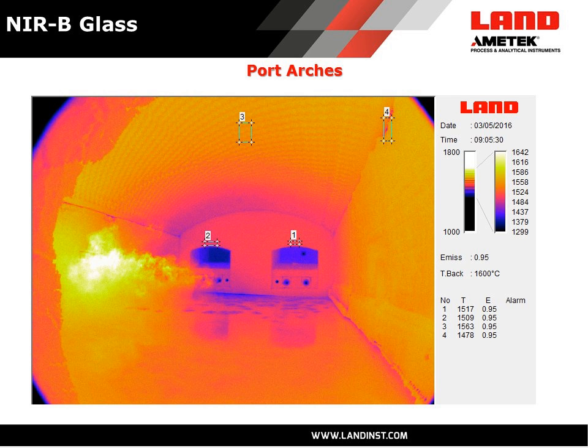Okay, so with this in mind, here's a thermal image of another end-fired glass tank. It's another customer. And in this particular case, they have set up 4 areas of interest within the scene. The first 2 areas of interest here are at the port arches. Okay, and you're able to record these temperatures live, and you're able to trend them, and you're able to replay them. So you're actually able to replay them and stop them at exactly the same point in time after each reversal and match temperatures very well, rather than thinking, oh, I'm not quick enough to start measuring temperatures.